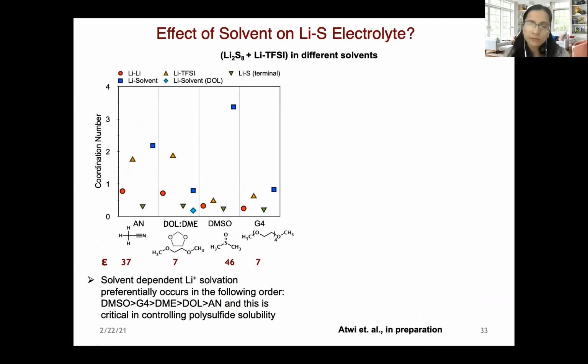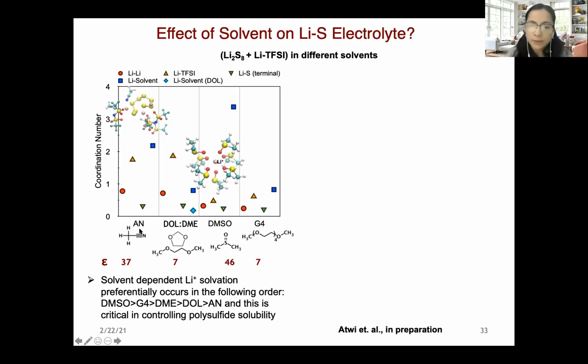And as a natural step, we next studied the effect of solvent molecules on the structural and dynamical properties. And here we considered a system of Li2S8 with LiTFSI solvent. And we looked at the coordination number of lithium with the anions, as well as with the solvent molecule. The trends that we found here were very similar to what we observed before for magnesium salts. So we found that acetonitrile provides very weak solvation and results in formation of aggregates in the solution. Okay. On the other hand, DMSO provides very strong solvation to the cation by binding through its polarizable oxygen atom, and can separate lithium from both the TFSI anion as well as the polysulfide species. DOL DME has similar trends as of what we observed for acetonitrile.